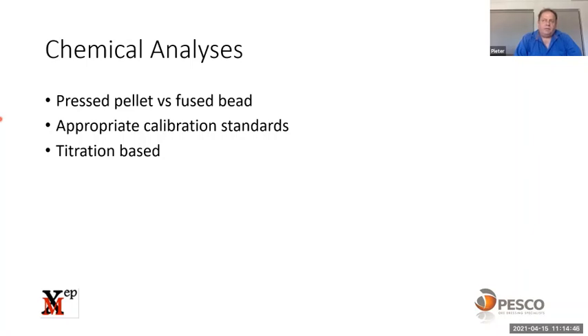From my experience, I worked at a lot of mines where they've got a very accurate press pellet calibration. They start doing a new exploration project. They look at a new area in a mine that's got a totally different type of matrix. And when I analyze it on the same press pellet, same calibration, sometimes it generates errors of 5 to 10% absolute values on the element that you analyze. So it's very important that when you do your analysis on a new ore body, make sure that you first test it independently at an accredited lab or a third-party lab to make sure your analyses are correct.